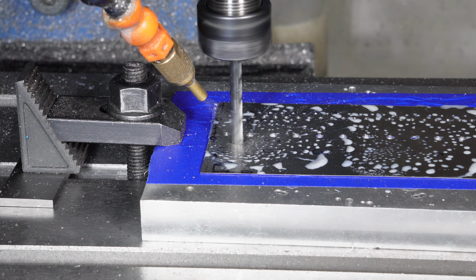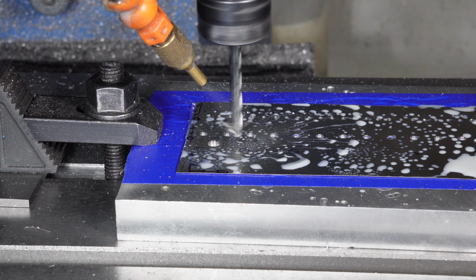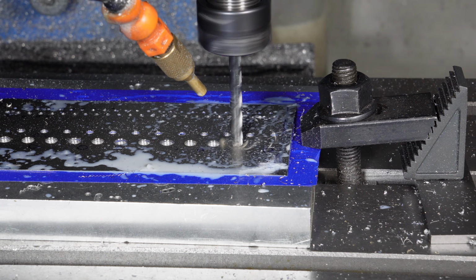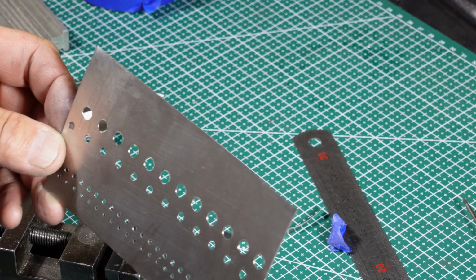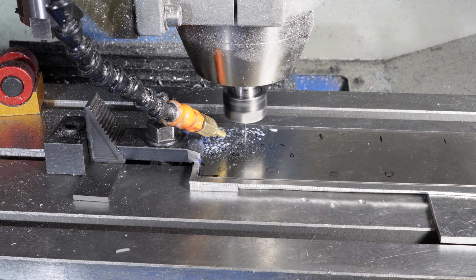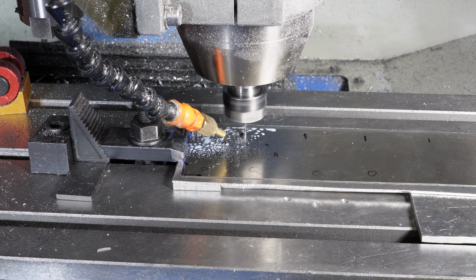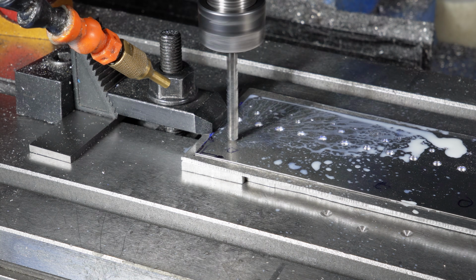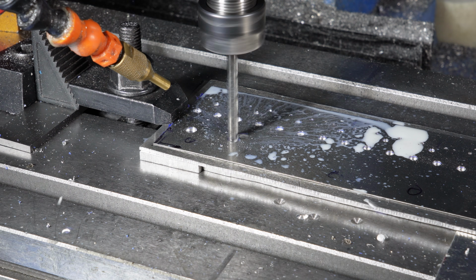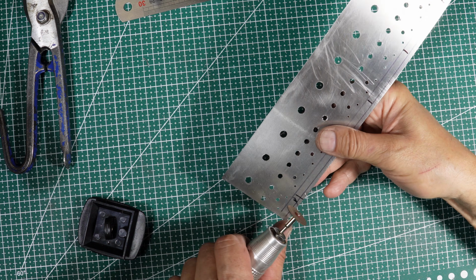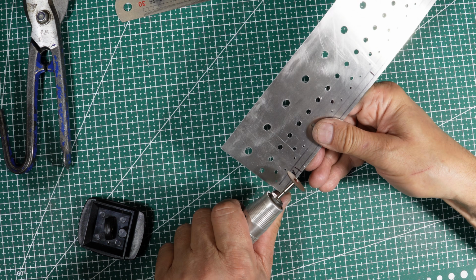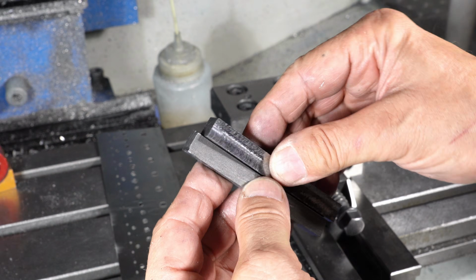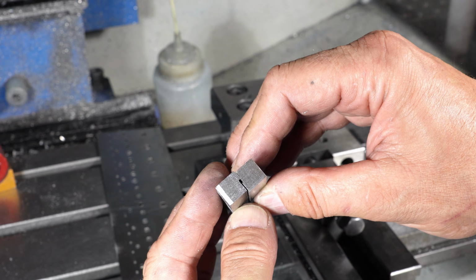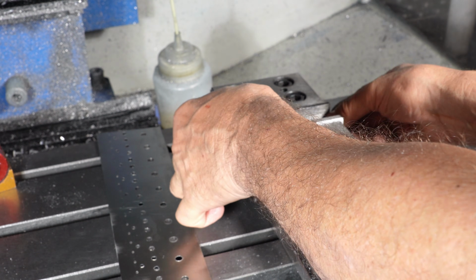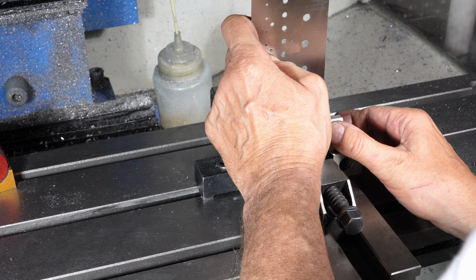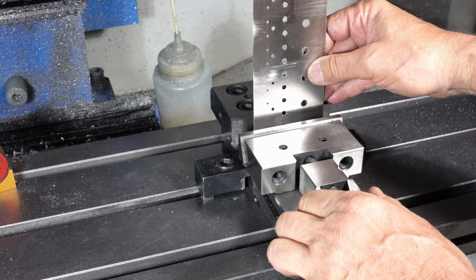Before any welding can begin, the combustion chamber components need to be manufactured. The inner and outer liners are machined from 0.3 mm stainless steel sheet. Machining material this thin can be surprisingly difficult, so I use the double-sided tape and cyanoacrylate method to secure the sheet to the CNC table. Once machining is complete, the part can be released easily using a thin scraper. The longitudinal seam uses a small Z overlap that I form using a simple custom-made tool. This provides accurate alignment and improves the rigidity of the assembly.